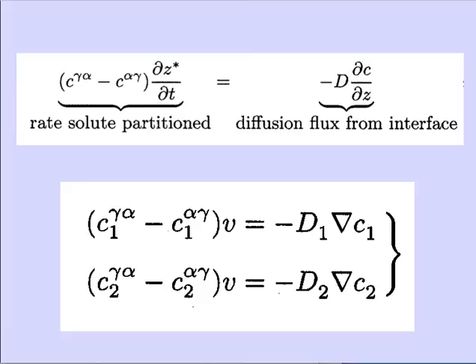There is a further complication: we could add another term D_12 times the gradient of component 2 - in other words, does the gradient of manganese influence the diffusion of carbon? If you have a completely homogeneous carbon concentration but a gradient of manganese, should the carbon diffuse? The answer is yes, because the concentration of manganese will influence the chemical potential of carbon. Do you know of any other scenario where the flux of something influences the flux of something else? Think about thermocouples - a temperature difference drives an electrical current. We will deal with irreversible thermodynamics in the next lecture, which is a theory between equilibrium thermodynamics and kinetics.